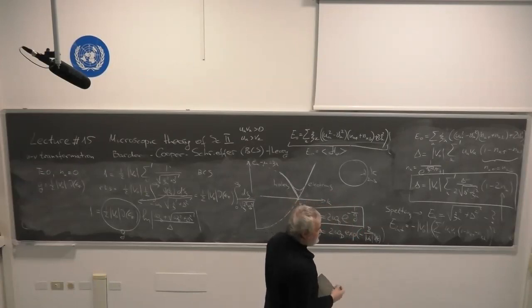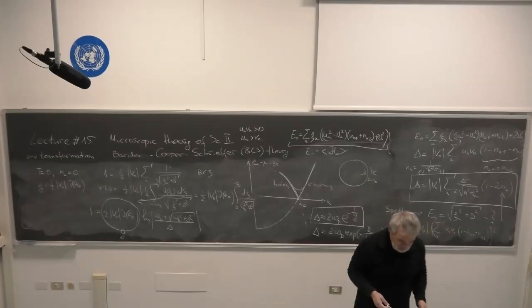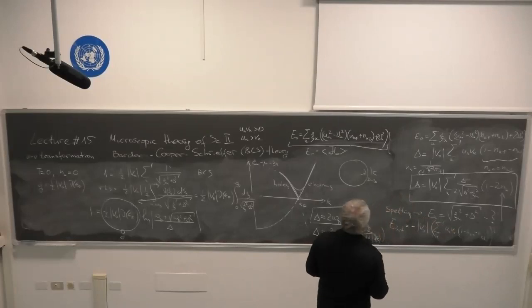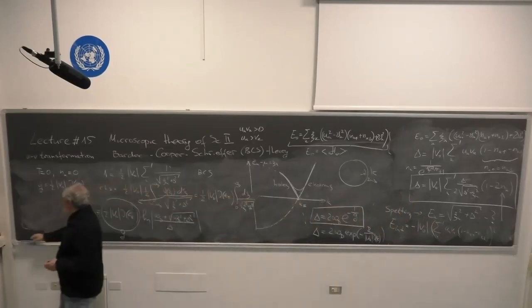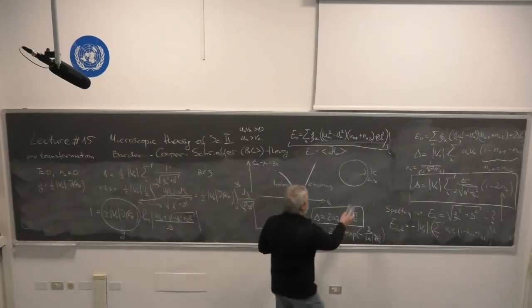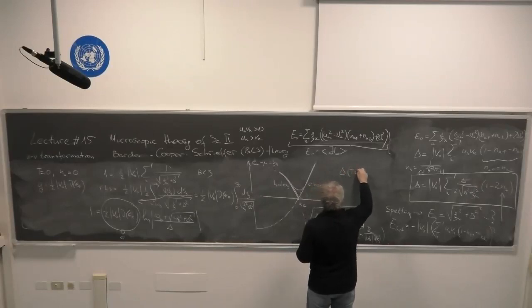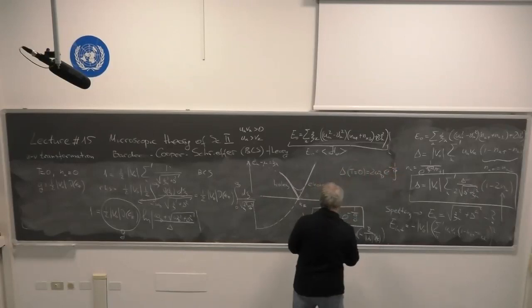The theory which I presented here is a sort of mean field theory, or molecular field theory. We will come to more discussion of what this molecular or mean field theory means when we discuss magnetism, when we meet several types of mean field theories, and we come to this discussion again. So, a very important message: delta at temperature equal to 0 is of the order of omega d e to the power minus 1 over g.